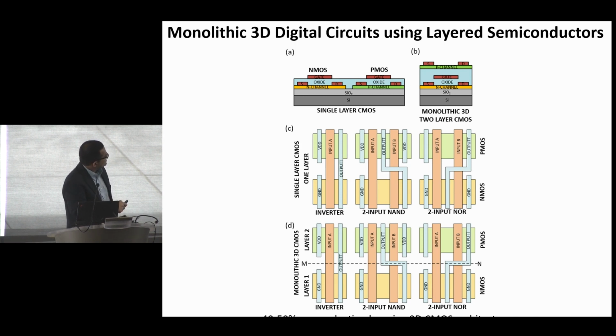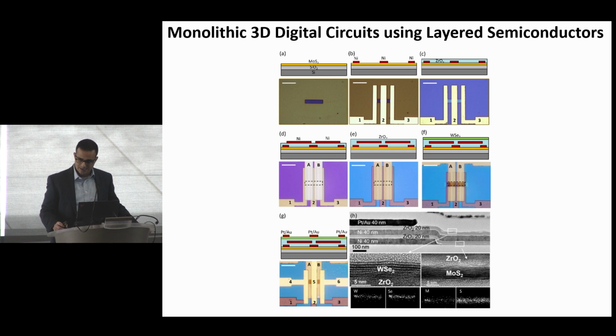You get about 40 to 50% area reduction by using this approach, depending on what logic or circuit you build. So these were some of the results from our earlier work, and you can see that we built devices. The way we did the fabrication was we first built devices on moly sulfide. So that's our NMOS. And then we built the PMOS on top. And from the TEM images, you can see where the PMOS layer is, the tungsten selenide, and the NMOS layer, which is moly sulfide.